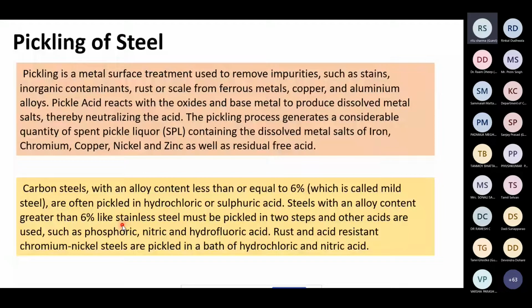Whatever acids are there, after some time they are exhausted, because the salts are dissolved into the water, into the acid, and this acid needs to be treated. Now this spent acid requires different types of treatment, but at the end of this acid treatment we generate sludge. So again we are generating sludge at the end of pickling. Pickling of the steel is a process which is inevitable. It is a must process, and it generates solid waste.